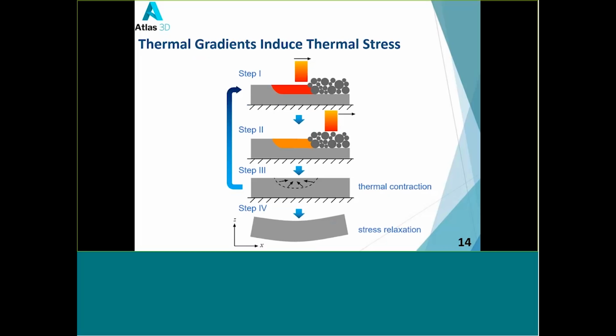From the thermo-mechanical point of view, the whole build process can be divided into 4 steps. So in step 1, the laser beam will melt the metal powder into a melt pool. In the second step, the melt pool starts to cool down by stirring liquid phase. In the third step, the melt pool is fully solidified, and the further temperature drop will cause lots of thermal stresses in that region. And step 1, step 2, step 3 will keep iterating during the layer-by-layer build process. And I call step 3 the thermal contraction, where this is where the stress is accumulated. And after we build the part, usually we need to cut the part off the substrate. And in this step, I call step 4, you will see lots of distortion of the part, and I call it stress relaxation.